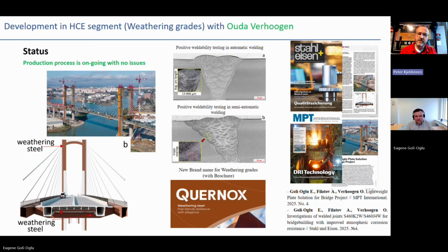I had the impression that when you add copper, you have the risk of hot tears or hot cracks. How do you avoid that when you're welding it? In this case, we are probably talking about higher copper addition, because to make this material good enough for atmospheric corrosion, we are adding 0.35% of copper, which is not so big for potential issues with the cracks, and still good enough for making corrosion index above 6.0, which is when steel is considered resistant to atmospheric corrosion.